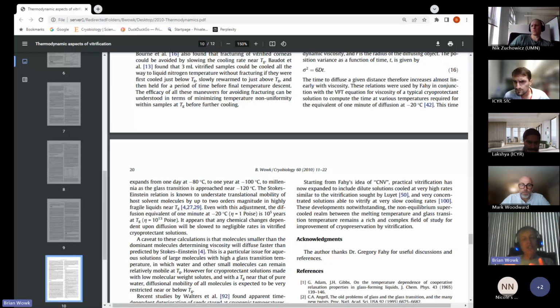The Arrhenius equation would actually predict a slowdown of chemical reactions on top of the slowdown due to viscosity changes, because the viscosity determines the ability of reactants to reach each other through the solution. Then the Arrhenius equation, once the reactants are in contact, determines whether they have enough thermal energy to overcome the activation energy for the reaction to happen.